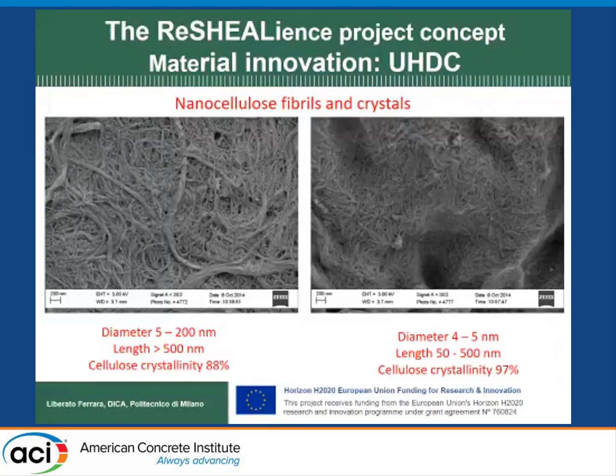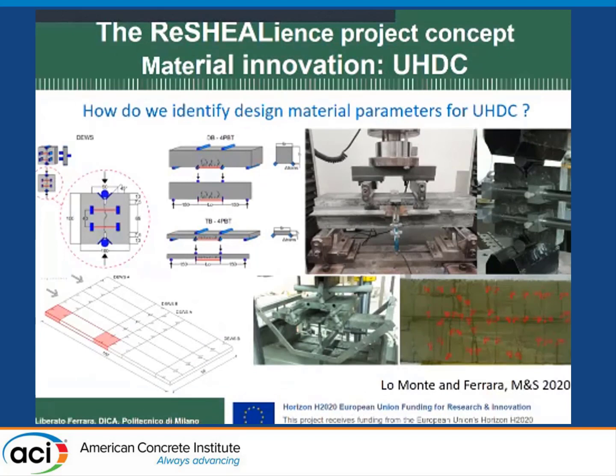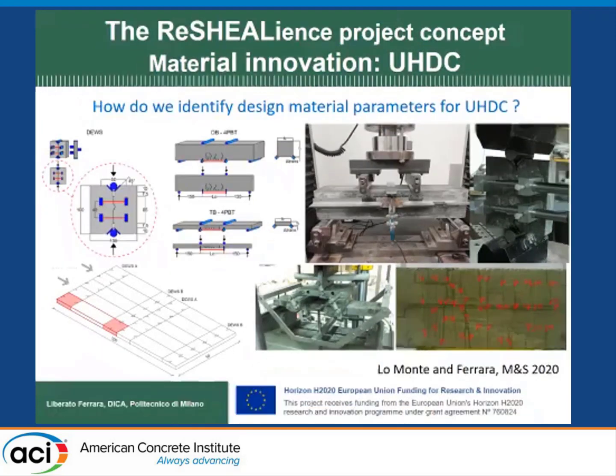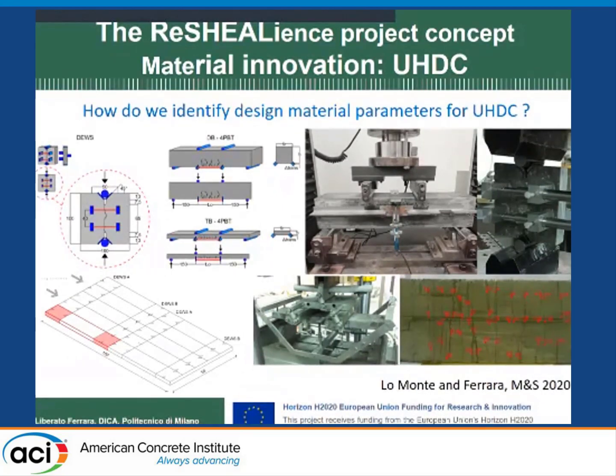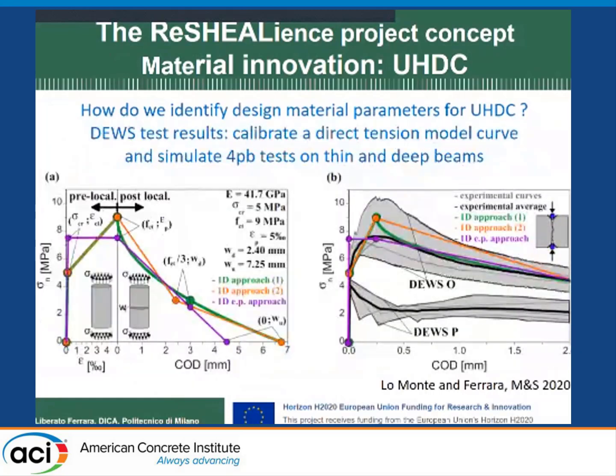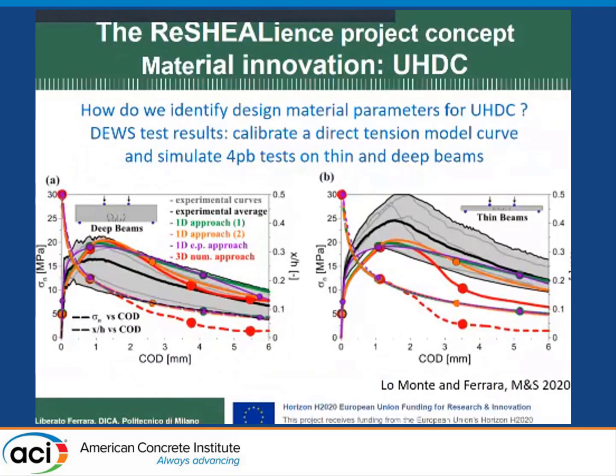So we performed an extensive mechanical characterization of the properties of this material because we wanted to identify the design material parameters. Bending tests on deep beams or on thin beams, in order to replicate also the issues of fiber dispersion that we expect to have in some of our structures. We performed an indirect tension test, the double edge wedge splitting you can see on the left, which we validated as capable of providing directly the tensile stress-strain constitutive relationship. So we identified different strain hardening or elastic plastic relationships from this double edge wedge splitting test, and we used them to simulate the flexural test both on deep beams and on thin beams.